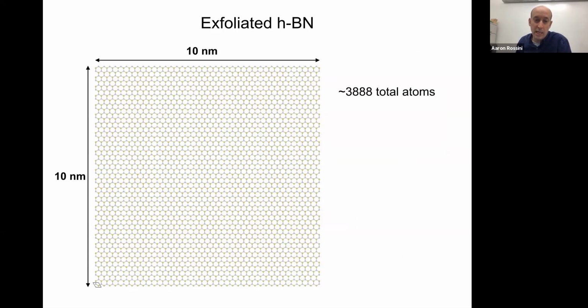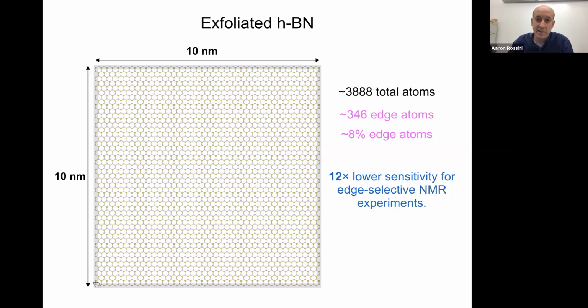Okay, so if we want to do NMR to look at the edges of these materials, there's a problem we have to address. The edge atoms, if that's what we're interested in looking at, make up a very small fraction of the sample. So this is a 10 nanometer by 10 nanometer hBN sheet that I made. It's got about 3,900 atoms. About 346 of those atoms are going to be found on the edges, so 8% of the atoms are edge atoms. What this means is if we wanted to do a hypothetical NMR experiment where we would only see the NMR signals from those atoms that sit on the edges, we're going to have 12 times lower sensitivity, which is going to translate to a 144-fold increase in the length of our NMR experiment.